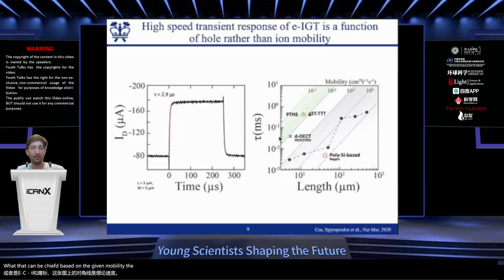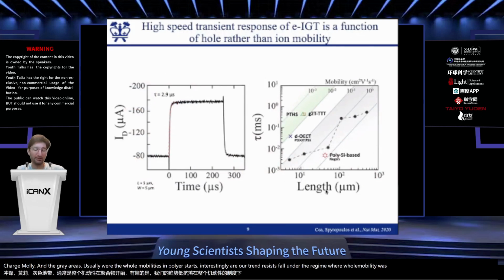The green area is usually where essentially ion mobility resides. They're a bit slower than classical hole mobility, it's just you're moving a charged molecule. And the gray area is usually where the hole mobilities in polymer start. Interestingly, our transistors fall under the regime where hole mobility was limiting the device.